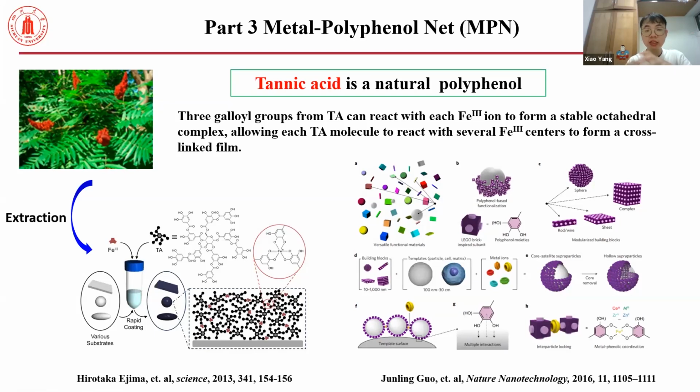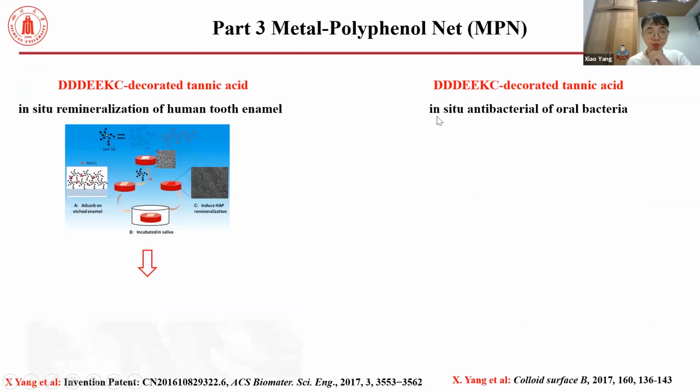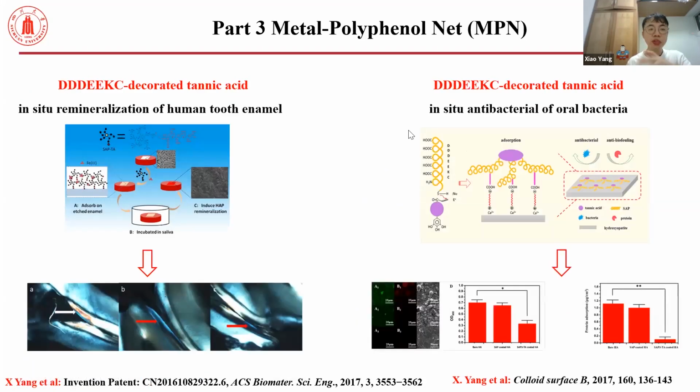So we think that this is very interesting. So in my research, we use the DDDEEKC to modify the tannic acid, and we also use the iron to complex with it, and it can form a layer on our tooth surface.